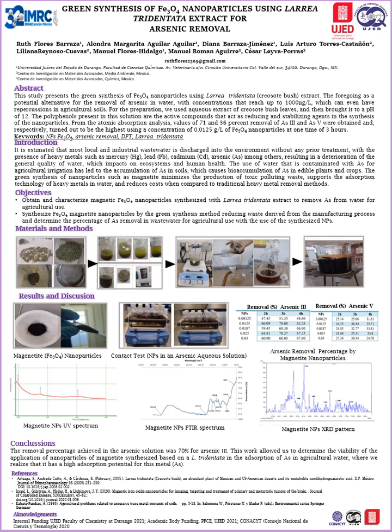The synthesis of the nanoparticles was carried out by means of the co-precipitation method, where 2 iron salts are used. In this case, iron 2 chloride tetrahydrate and iron 3 chloride hexahydrate using a 1:2 molar ratio and 100 milliliters of deionized water respectively. Firstly, 99.5 milliliters of deionized water were preheated at a temperature of 80 degrees Celsius, and upon reaching that temperature, the salts are added, constantly stirring for 10 minutes until the solution turns slightly brown.